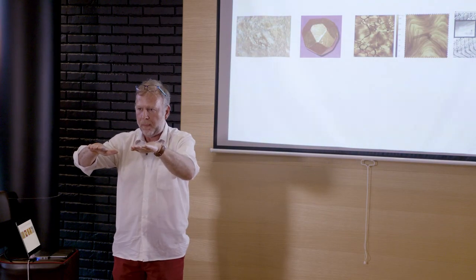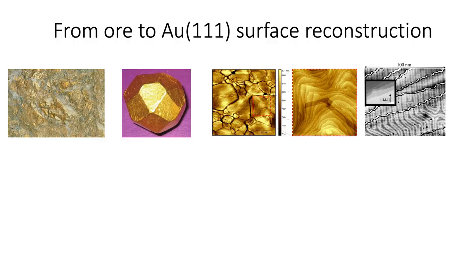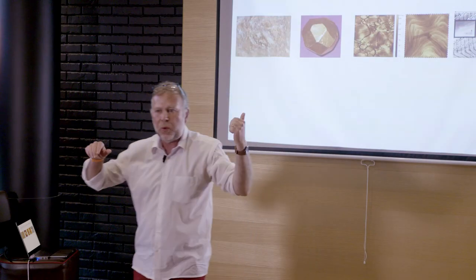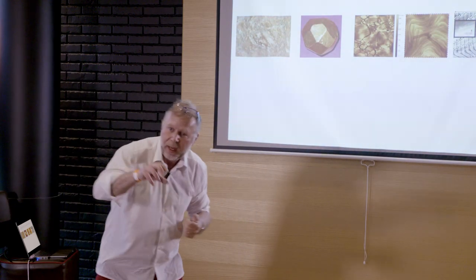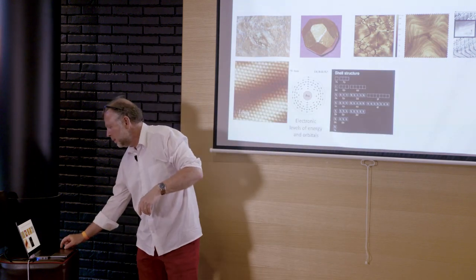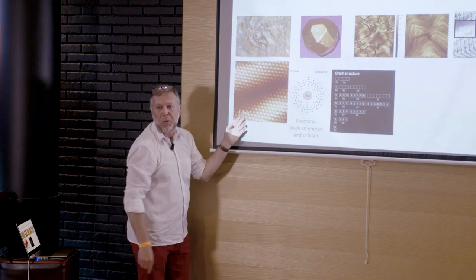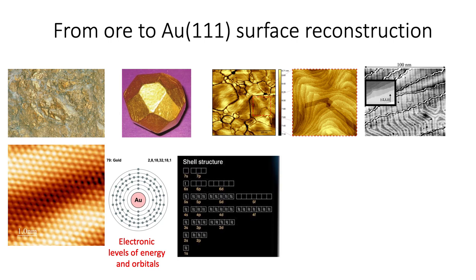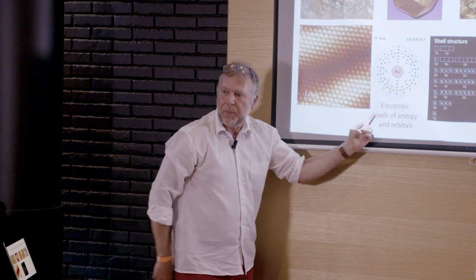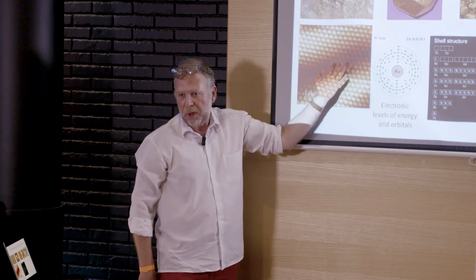We flatten everything to have a better contrast. And what we see here is the steps. But here, it is the atomic arrangement of the surface of gold. And we zoom again. You see, you have parallel lines, and we zoom again. These are two parallel lines. But you see, the scale is very, very small. This is 1 nanometer. This image is 10 nanometers. It's very small. And there are 525 pixels in this direction, 525 pixels in that direction. 1 minute to make this image.